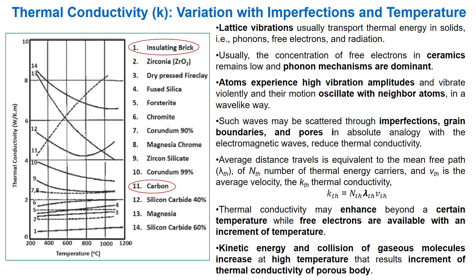Now we will discuss the thermal conductivity of refractories. Usually phonon mechanisms dominate in ceramics, where atoms experience high vibration amplitude and vibrate violently, oscillating with neighbor atoms wave-like. Such waves may be scattered through imperfections, grain boundaries, and pores — in analogy with electromagnetic waves — reducing thermal conductivity. It is defined as the product of number of thermal energy carriers, mean free path, and average velocity. Thermal conduction may increment with temperature, particularly in carbon and porous refractories, attributed to free electrons and enhancement of kinetic energy and collision of gaseous molecules in the porous body, respectively.